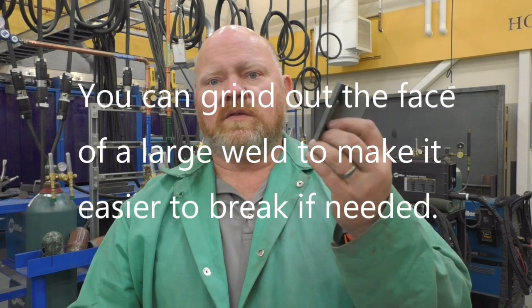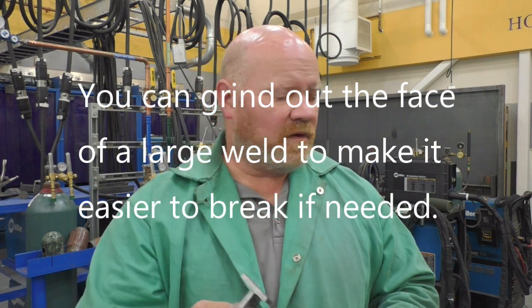So I can do a little test piece. I've got these right here, and I'm going to turn the camera and get a hammer and the vise, and we're going to bust these things and take a look at them. This was welded with flux core, same process I used here. Basically it's a tack weld, but if that's all I can test, then that's what I'm going to test when I'm at home. This one was welded with my Miller-Matic, but it was down at 19 and a half volts and 260, I guess, inches per minute wire speed. So basically it mimicked my wall outlet plug-in Lincoln 110 MIG welder wide open, okay? And I suspect that this is not going to have much penetration. It's not going to pass.